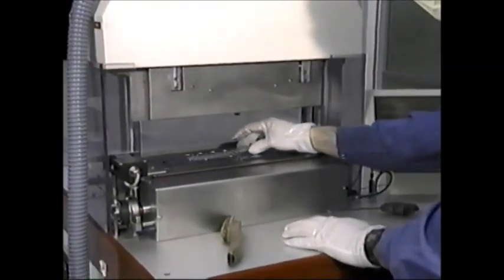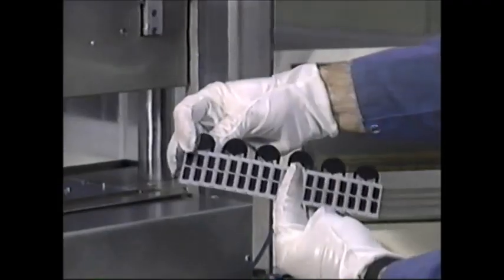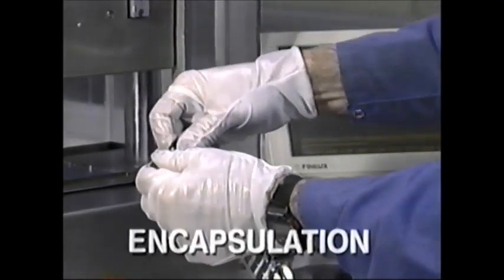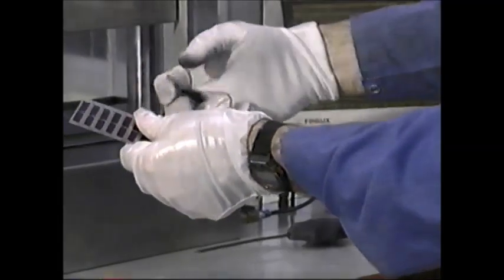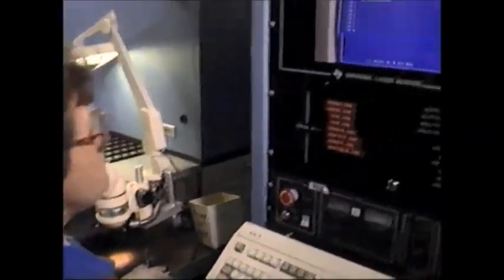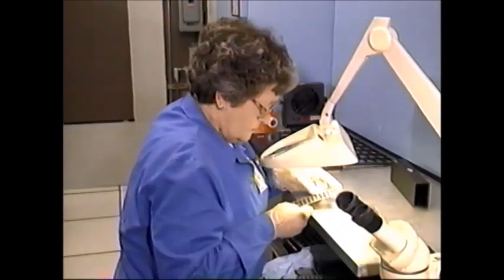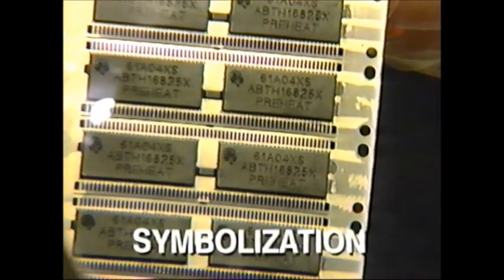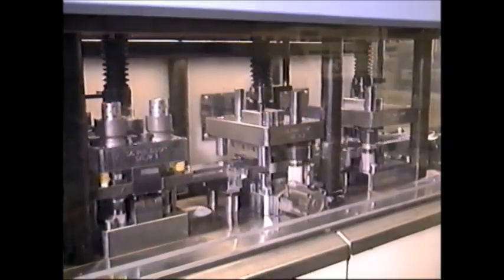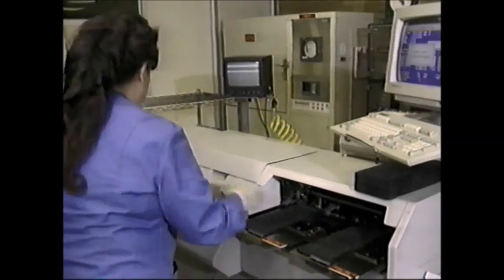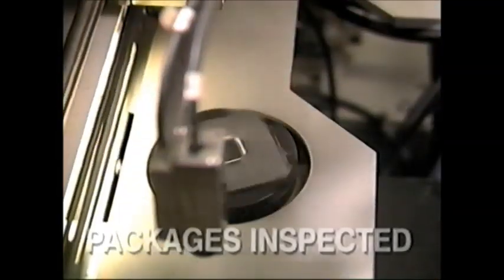Once the chips and lead frames pass inspection, they are placed in a mold that forms the final package. Plastic epoxy or ceramic material is usually used for encapsulating the chip. While the microchip lead frames are still together, the packages are printed with part number, logo, and lot number, a process called symbolization. The microchips are then cut apart by a large press, which bends the leads at the same time. The packages are electrically, electronically, and mechanically inspected, and each part is screened for defects, such as cracks in the plastic, uneven plating, or poor trimming.